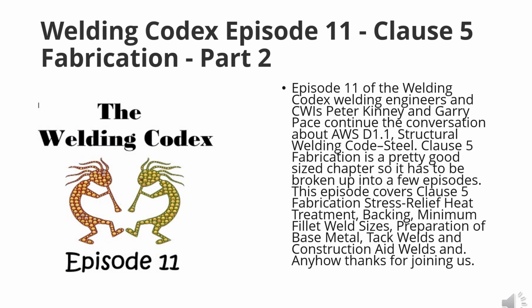That's why we've got to try and follow the rules. Tack welds that are not incorporated in final welds and construction aid welds that are not removed shall meet the visual inspection requirements before a member is accepted. Tack welds, you can't have cracks, you can't have porosity, you can't have a bunch of defects, or your tack welds, if they're going to be incorporated into the final weld, they need to be quality.